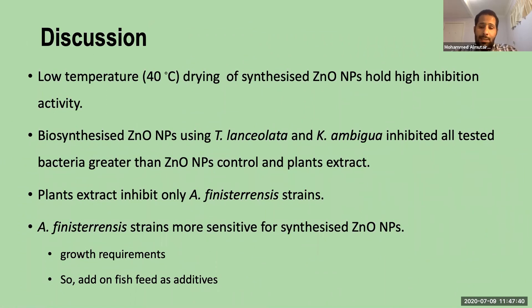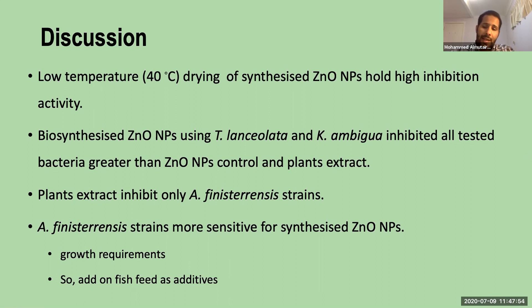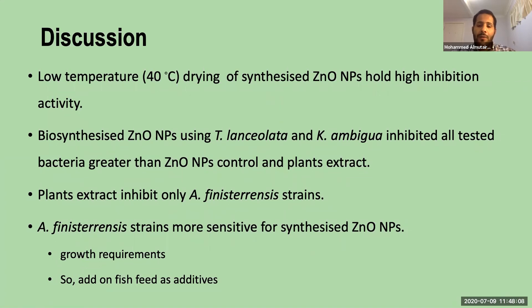Now let's discuss our results. The method of synthesizing green zinc oxide nanoparticles was modified to obtain nanoparticles that might hold high antibacterial properties by using a low temperature of 40°C, particularly during drying, to maintain the integrity of biochemicals extracted from the plant leaves. Other studies have used high temperatures which might affect the active chemicals.